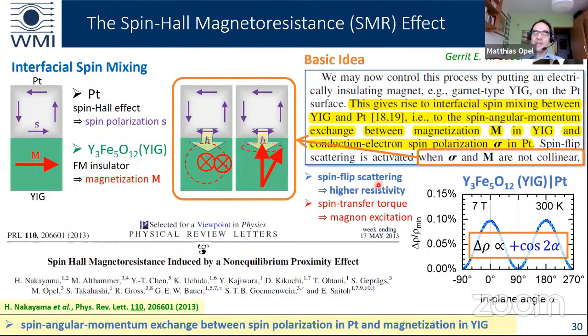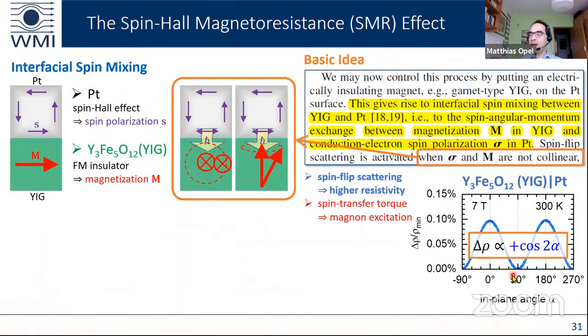And this higher resistivity is responsible for this characteristic oscillation. So what we have here is the in-plane angle alpha. If the angle is 0 degrees, then we have a higher scattering. If the angle is 90 degrees, we do not have that, because we assume that the magnetization of our YIG follows the external magnetic field that we apply under this angle.